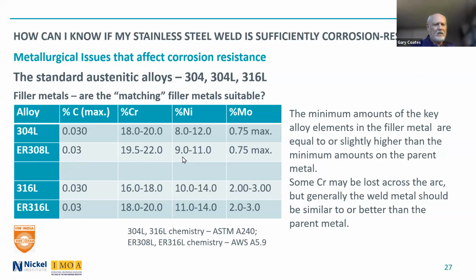The nickel content is in the middle. It's less important from a corrosion point of view. And 316L plate versus 316L bare wire. Again, you can see the chromium content, which is the element most likely to be lost in a weld, is higher than the parent material. And so therefore, yes, the matching filler metals, they're not actually matching, they're slightly over alloyed. They are suitable in most cases.